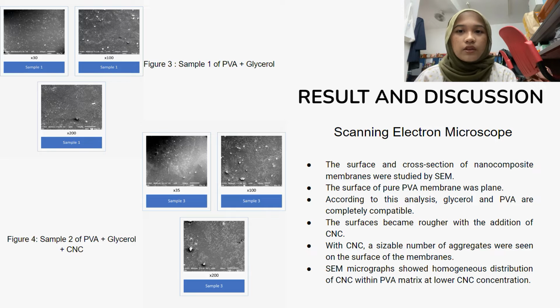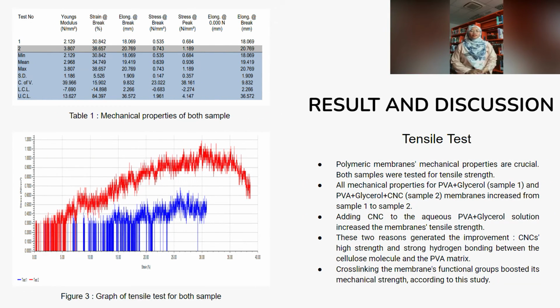Just like in OM, the surface become rougher with the addition of CNC because of the aggregation. With CNC, a multiple number of aggregates were seen on the membrane surface. With low CNC concentration, SEM was able to show a homogeneous distribution of CNC within PVA matrix. The mechanical characteristics of polymeric membranes are one of the factors that are considered to be among the most essential. The membranes based on the PVA that were produced were put through tensile testing so that the level of their mechanical strength could be determined.